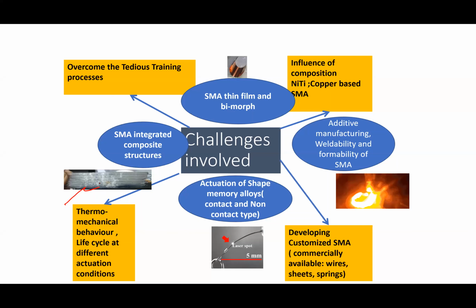In order to achieve the austenite or martensite phase, I need to heat it in a furnace near the austenite region, and then I need to bring it back to the martensite region by putting it in a liquid nitrogen environment. This cycle I need to repeat to get a displacement. So it was a bit tough for us to reach that particular level. These are some of the major challenges which we were trying to address in our research focus.